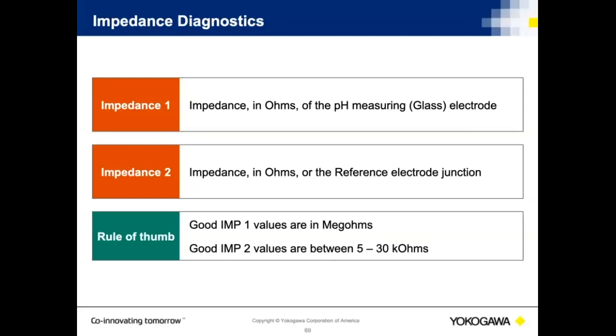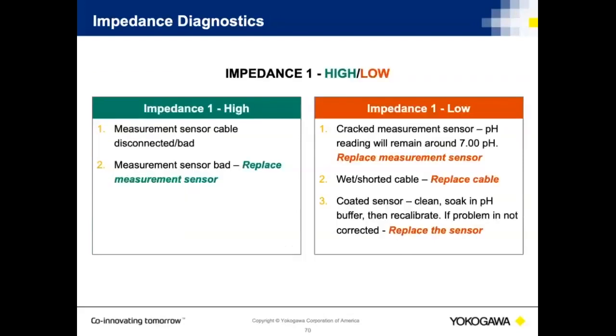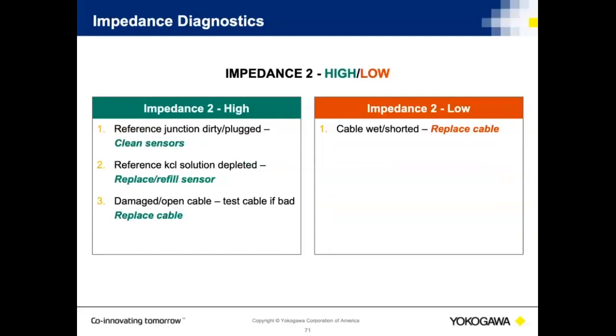Impedance for the reference electrodes can be as low as 2 kiloohms to 30 kiloohms. When they start to get much above that, that usually means that I'm having plugging issues or coating issues occurring. Some good things to do here. Measuring sensor cables disconnected, because it's high or low, high. Measuring sensor is bad, replace the sensor. The key with pH probes, if you can't calibrate them in solution and you see these values getting out of tolerances, what you do is you replace the electrodes. Again, you try cleaning first, but the typical issue is that they've gone out of tolerance.